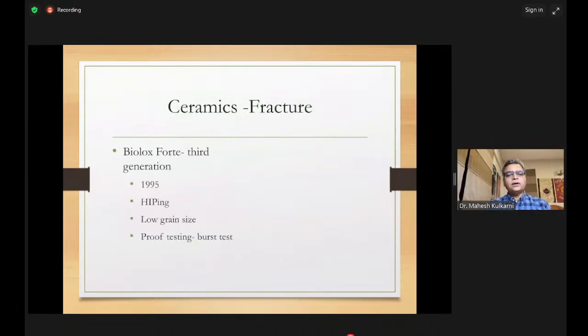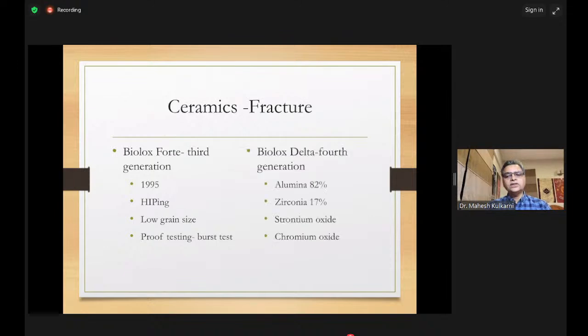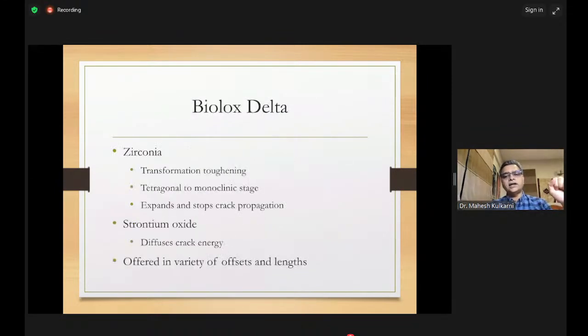The Biolox Forte, or the third generation ceramic, was started manufacturing in 1995. Hot isostatic pressing was used for it. The grain size was reduced and proof testing was done. And I think we did much better than the first generation. And the Biolox Delta, or the current ceramic that we use, which is pink in color, which is a combination of alumina and zirconia, along with the strontium oxide and chromium oxide platelets, which will prevent a crack from propagating. It will act as a shock absorber, and the zirconia itself is actually extremely tough. So alumina is made tougher by addition of zirconia inside it.